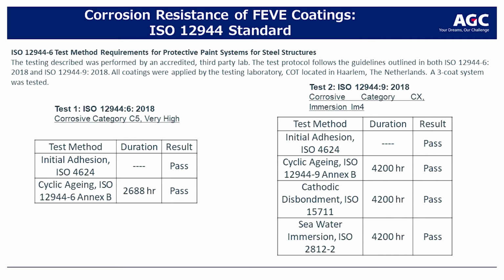The second test is actually an immersion test. We usually don't use these materials in immersion, but what you can see here is that the 3-coat system does pass that immersion test, and you don't get much cathodic disbondment. In other words, if you have cathodic protection on a metal substrate, the coating is not going to delaminate because of it. They also tested in seawater immersion, and it passes as well.